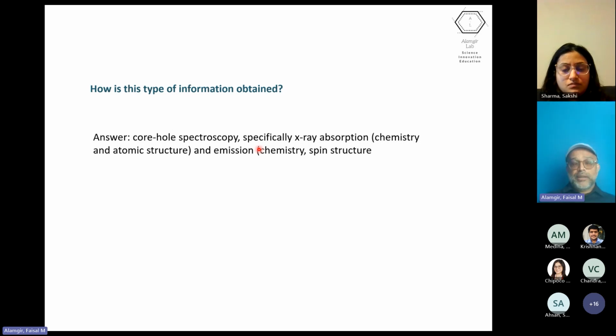And so here, in many cases, we can actually design reaction cells where we can observe the reaction in real time, because the X-rays are able to penetrate into the cell through windows, observe what's happening, and the signal information comes out, obviously slightly attenuated, but still sufficient to give us the information. The same thing is much harder to do with photoelectron spectroscopy, although a lot of advancement has happened in near ambient pressure or ambient pressure level XPS.